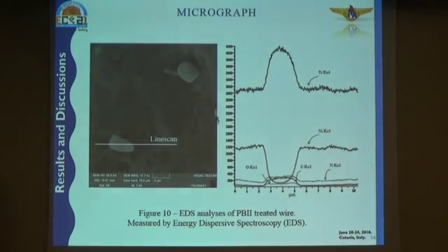This is another micrograph of the treated wire. We have this titanium carbide exposed in the surface. It is exposed because we did an etching before treatment, and we confirmed its chemical composition by a line scan made in EDS, as we can confirm here. And we see the nitrogen now over the surface. It is implanted.